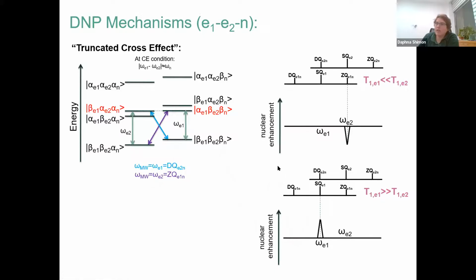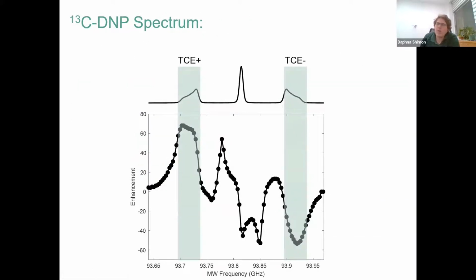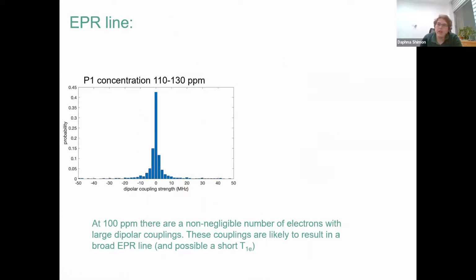And so the truncated cross effect seems to match what we're seeing here, because we are seeing positive enhancement on one side and negative enhancement on the other. And if that's really what we're seeing, then what we need is another electron pool that has a very fast relaxation time that's shifted slightly inward from the actual line that we measured. And that would give us the correct signs. So the question now is, do we expect that kind of EPR line, another pool with fast relaxation?